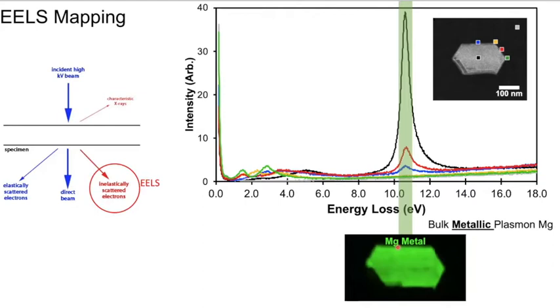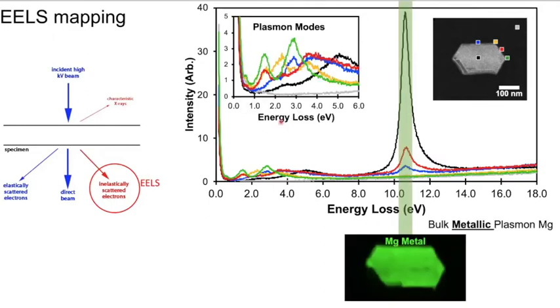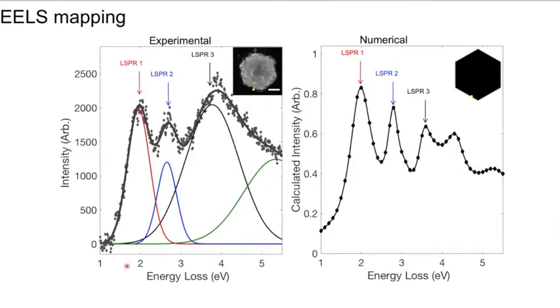All right, but if we go back to localized surface plasmon resonance, if we look at the other positions and zoom in, we start to see various kinds of peaks appear depending on where we put our beam. Of course, we don't just do six measurements. We're actually going to do a map through the entire particle and extract from that where the intensity of, say, the peak here at 1.3 eV is, and so on. And so here's an example of another single particle measurement. This is the very first measurement we did on these. This is a hexagon, and you see that it has a number of peaks